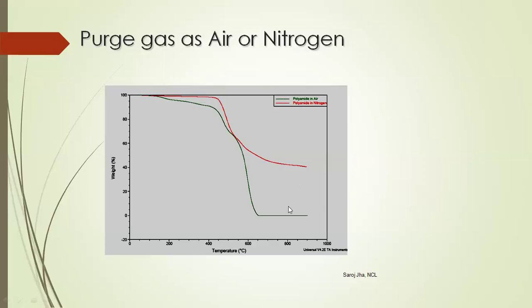450 and the expected residue around 40%, because this is a fuel cell catalyst which we are using, which is a 40% catalyst. So here, if you see, I'm getting residue as 40%. So nitrogen is the proper environment, not the best, for my fuel cell catalyst.